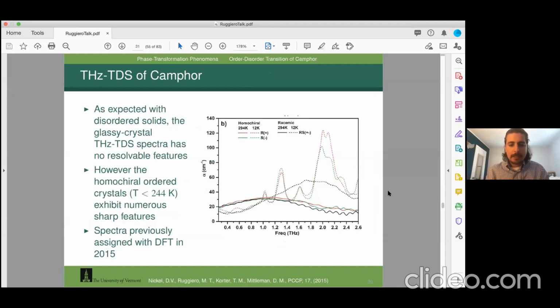The terahertz spectra of the ordered phase are these red and green dotted lines, and you see nice spectral features, which is common of a crystalline material. But the solid red lines down here are the plastic crystalline terahertz spectra. It's a disordered crystal, there's no discrete transition, and it's not really easy to understand.